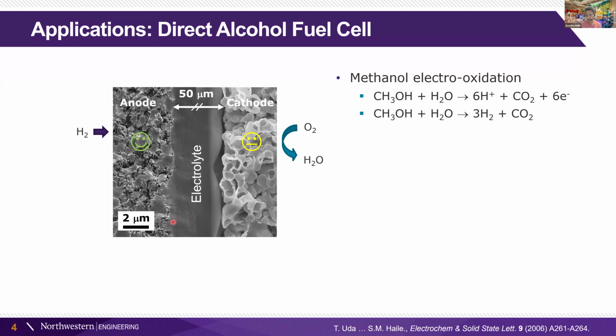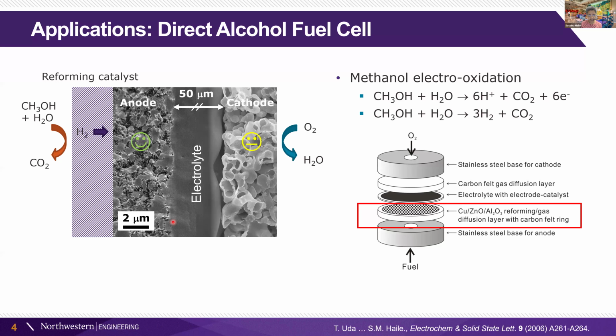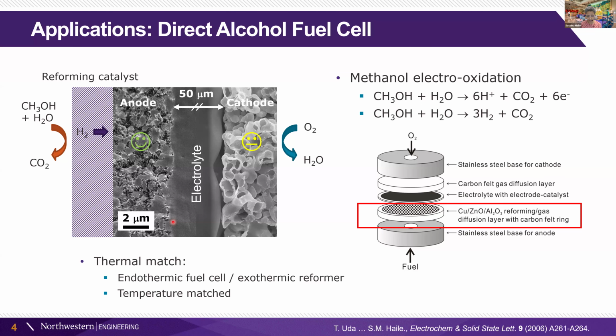And what we are relying on is the fact that methanol is a bioproduced fuel, so the CO2 would be recycled. What we see here is the way that we do it is we put in a reforming catalyst to allow the methanol to do that first step, which is to react with steam to produce either directly protons or produce hydrogen. We suspect that it's a two-step reaction where we're producing the hydrogen first and then that gets consumed at the anode. And there's a very good thermal match here in the sense that the exothermic reaction of the fuel cell is releasing heat because it's not 100% efficient, and the endothermic reaction of the reformer requires heat.